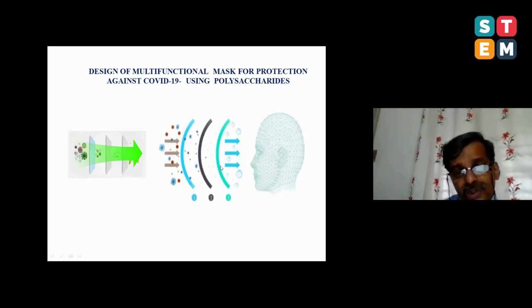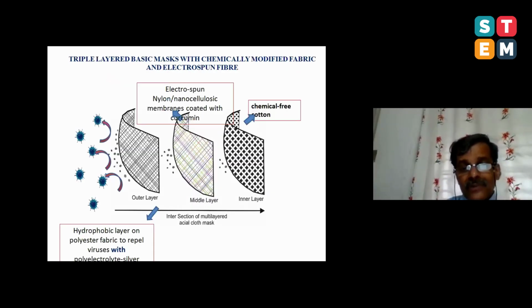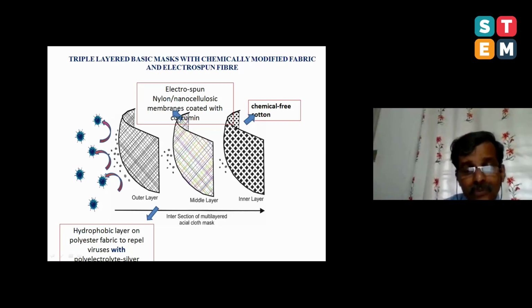And the innermost layer of this mask is made of cotton because it's very close to your mouth. So it's an eco-friendly material, cotton. And this is our construction. The inner layer, which is chemical free, is made of cotton. And the middle layer is made of electrospun nylon coated with nanocellulose with a lot of positive charge and some curcumin. The outer layer is made of polyester with a polyelectrolyte coating. So this polyelectrolyte coating can repel all the coronavirus.